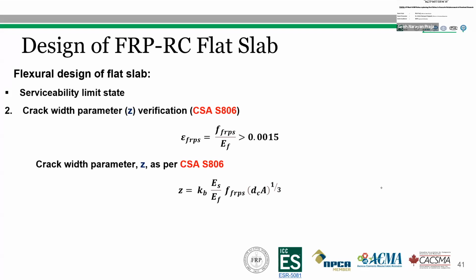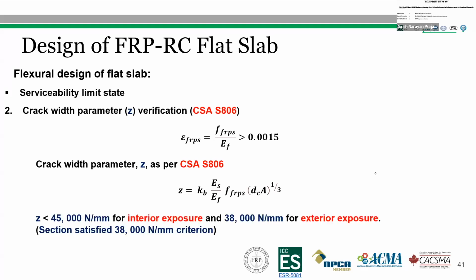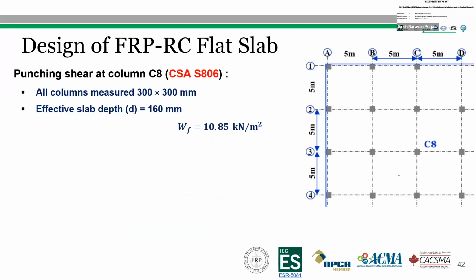So the crack width parameter Z as per CSA S806 could be checked using this equation, and the value of Z should be less than 45,000 Newton per millimeter for interior exposure and 38,000 Newton per millimeter for exterior exposure. And in a parking flat RC slab, it should satisfy the 38,000 Newton per millimeter criterion. So we did the required check for serviceability.